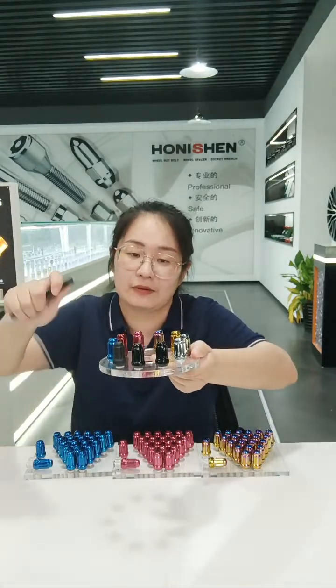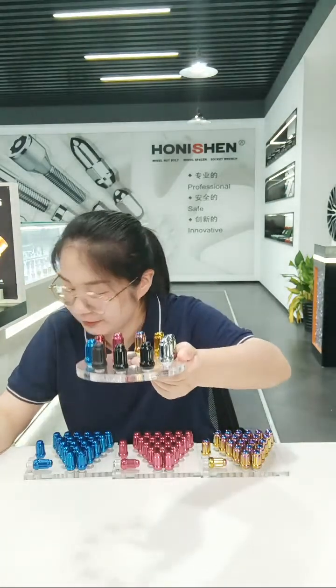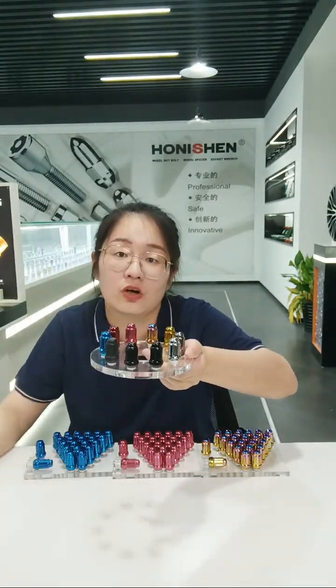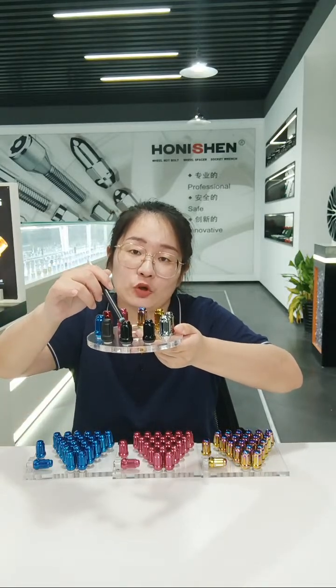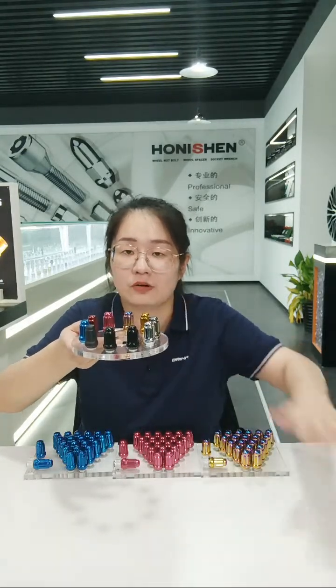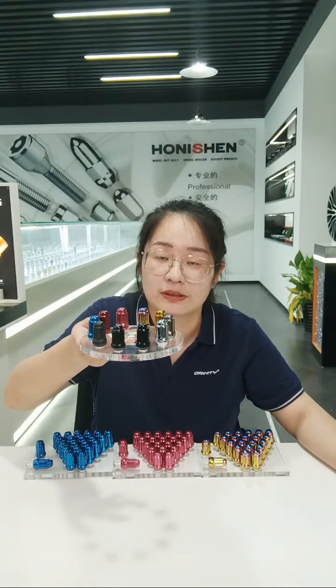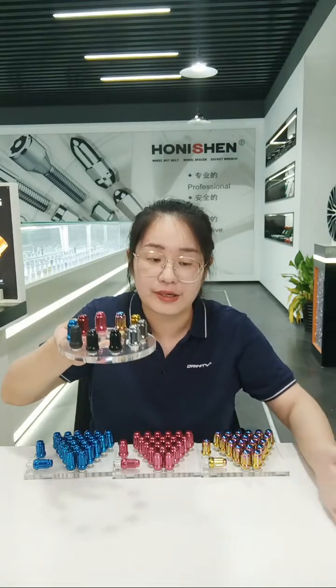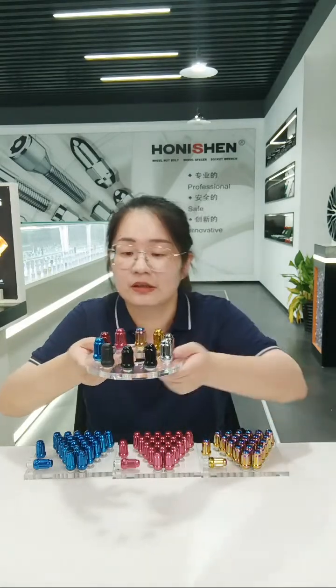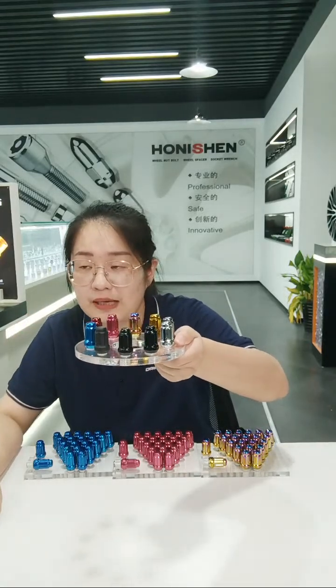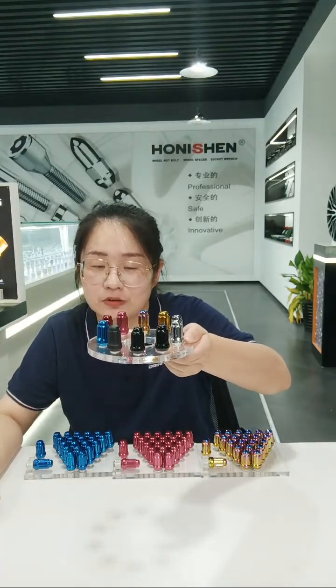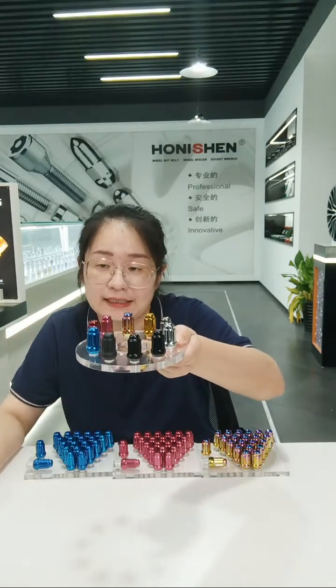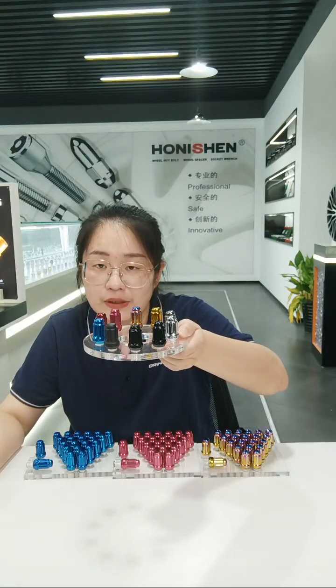There are 3 blacks here: 1, 2, 3. Do you know the difference between them? This we call black chrome. This is black electrophoretic, and this is matte black. There are 3 differences between them. First is anti-rust performance. Black chrome could pass over 72 hours, 96 hours salt spray test. Black electrophoretic could pass over 48 hours salt spray test. Matte black could pass over 200 hours salt spray test.